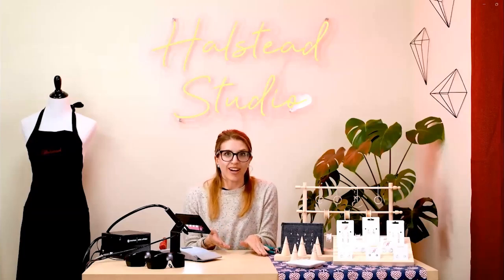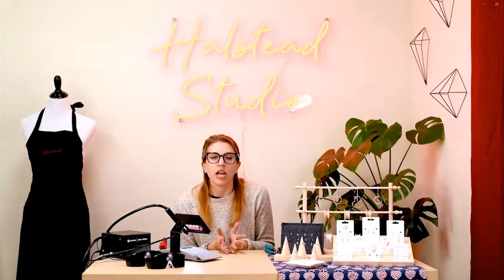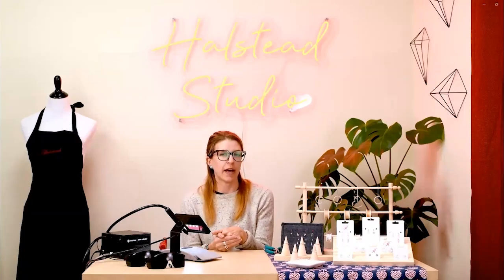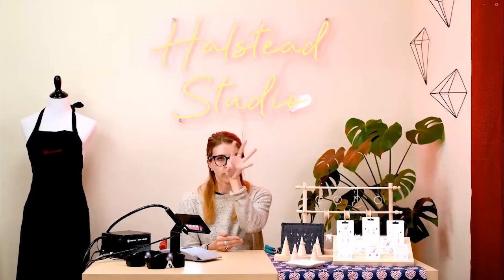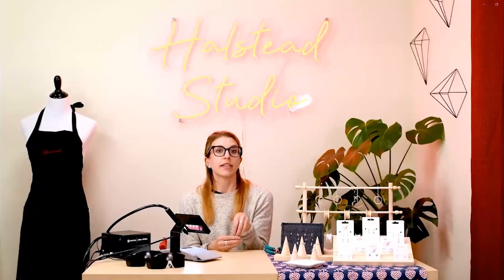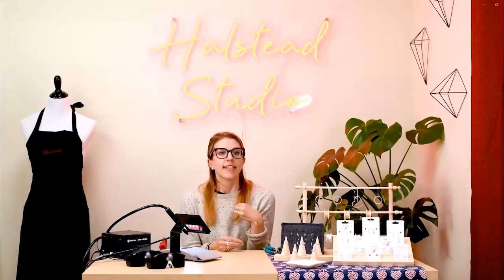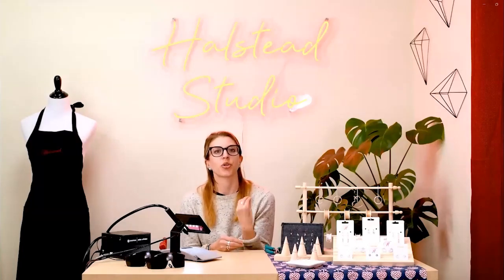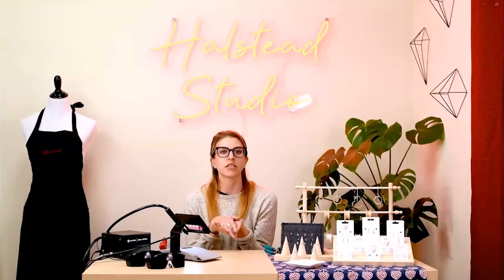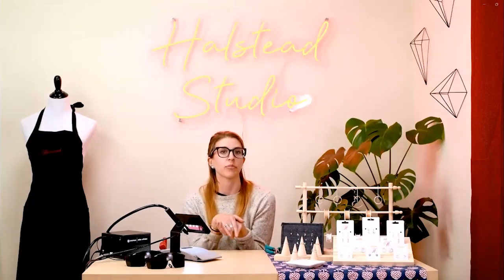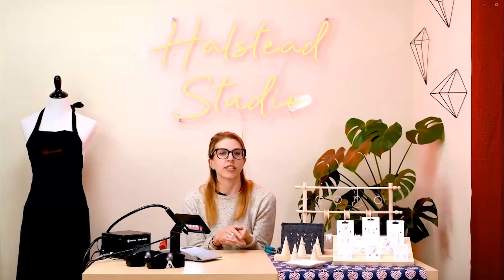Now, we know that not all clients are going to be able to afford that, so just be very mindful of that. And if you are using gold filled, always make sure that you use filler wire to weld those jump rings or chain links. Because when you're doing that weld, what you're doing is you're melting all of those layers together. So that little spot where your weld is can turn black or tarnish or discolor, because what it's done is it's melted those layers together and it's no longer pure gold on the surface, which tarnishes